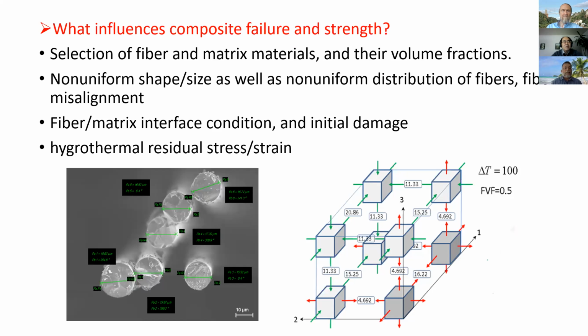composite. But some other parameters, such as the shape, size, and more importantly, as also discussed in the previous presentation, is going to be non-uniform distribution of fiber and fiber misalignment. Unfortunately, we cannot control those that well. And also, depending on the curing process and also the material, the fiber matrix interface condition, we cannot control that well, and we have to accept it as it is after the curing process.